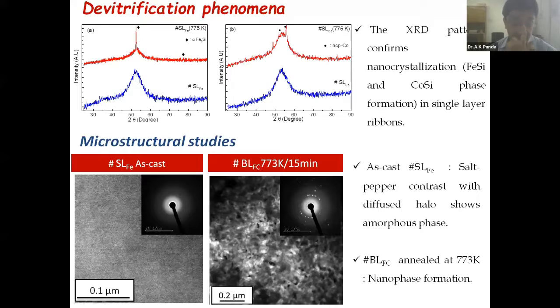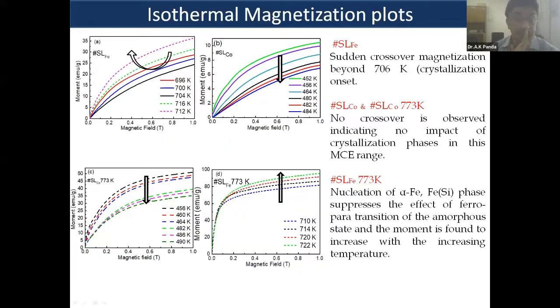These are the TEM micrographs. You see when you anneal it, it gives a salt and pepper structure like nanoparticles dispersed in the amorphous matrix. And when we try to find out the moment versus magnetic field, the first on the left side is the single layered iron ribbon. The top two are the single layered iron and single layered cobalt. You find that there is a change, an inversion, in the magnetization plots. The inversion is due to the change in the crystallization.